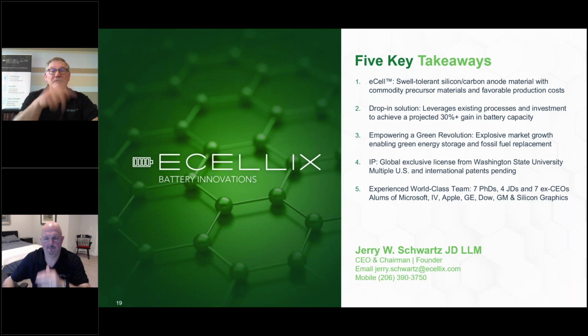So if you just take the graphite out and you drop our solution in, you immediately are looking at a 30 to 50% gain in battery capacity, and also having additional volume, because we're about 1/3 less volume and 1/3 less weight. Thinking of a car, it's a smaller battery and less weight to deal with, which allows us to put more cathode in and project greater energy into the battery.